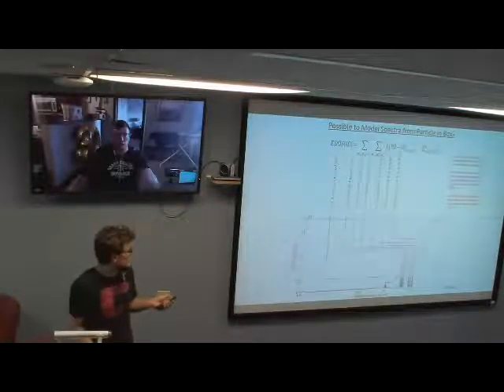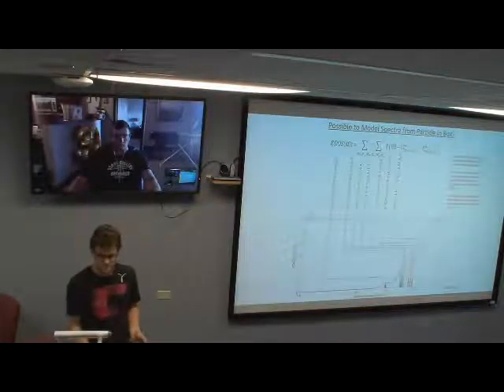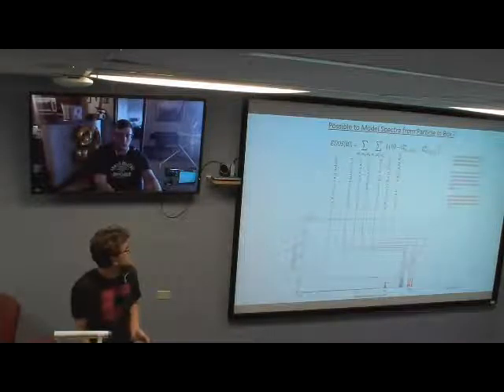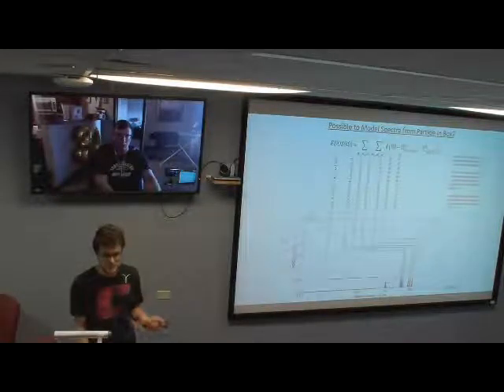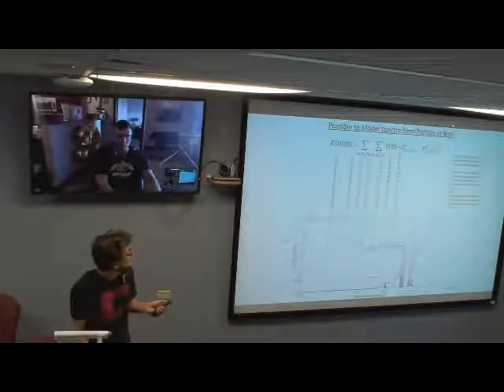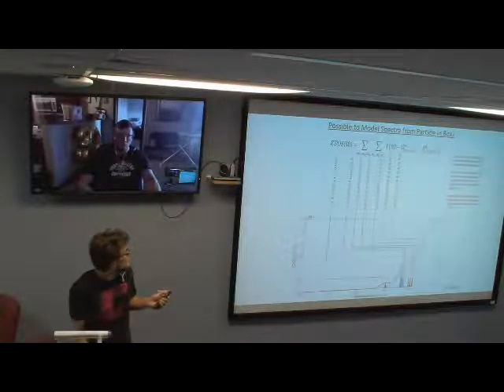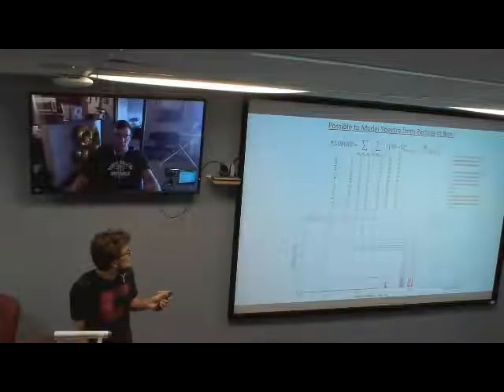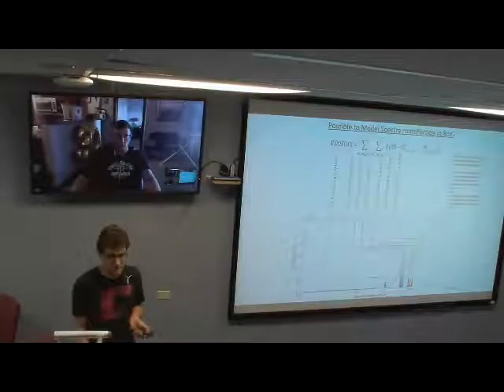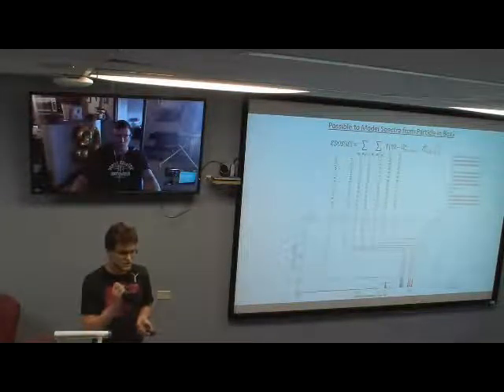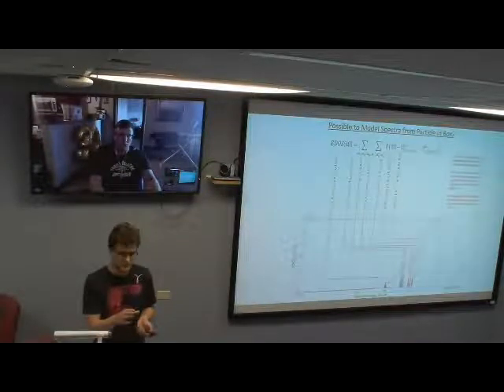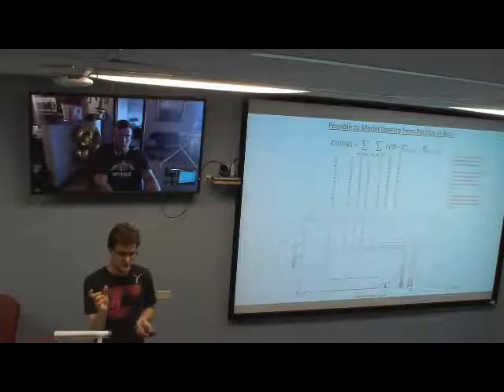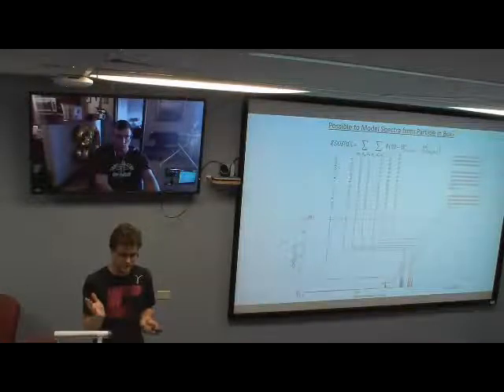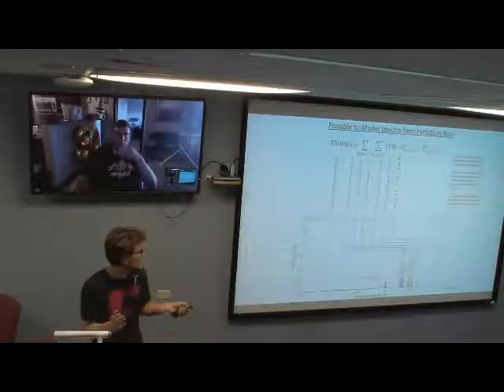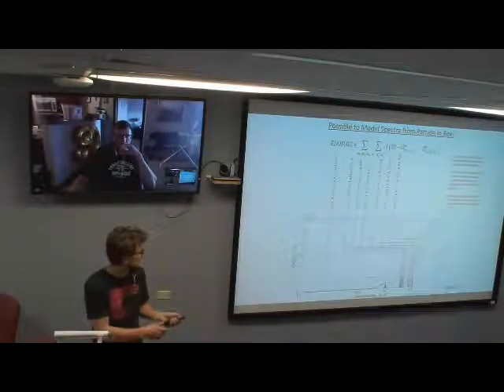Yeah, so just to continue our particle in a box modeling, we tried to see if it would be possible to model spectra just from a simple particle in a box model. The first initial thought was using the energy density of states. Basically, you just consider every transition and bin it into a histogram. You just account for all possible transitions, and they're all equally likely within a certain energy range. You plot them and give them a little broadening for spectra. And that's what this chart is here.